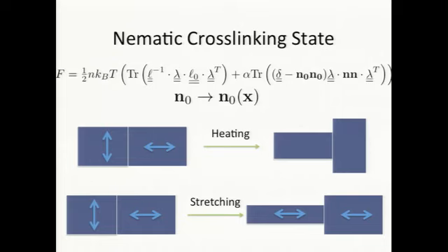Now, suppose we do the opposite. Suppose we cool our liquid to a nematic state, and then we cross-link. So now all bets are off, right? So now there is nothing that says you can't have one domain like this and one domain like this, because they nestled up like that next to each other in a liquid when there was no constraint of kinematic compatibility, and then you turned it into a solid. So even though these states still have perfectly soft local modes, they can't realize them, because if you imagine trying to stretch an ensemble like this, this one, I'm stretching in the horizontal direction.